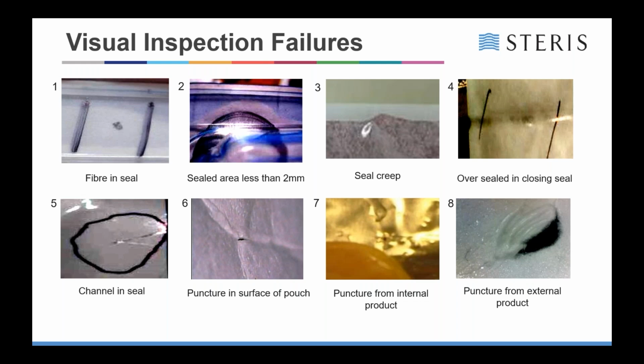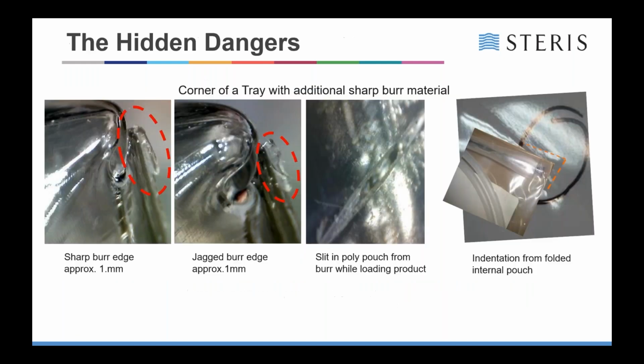Where you have oversealed pouches or seals, the material has started to melt and become transparent, indicating that it's going to start to become brittle. You have channels in the seals, pinholes in seals, tears, cuts, rips. Again, you can have all of that in any part of the actual pouch itself.